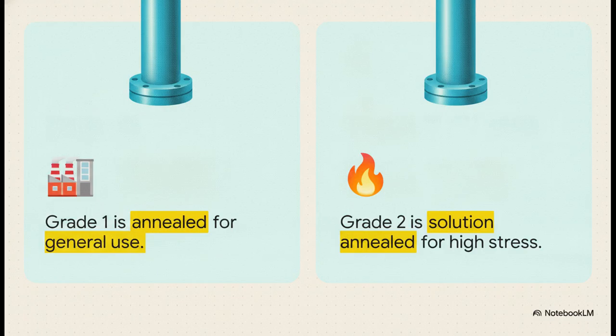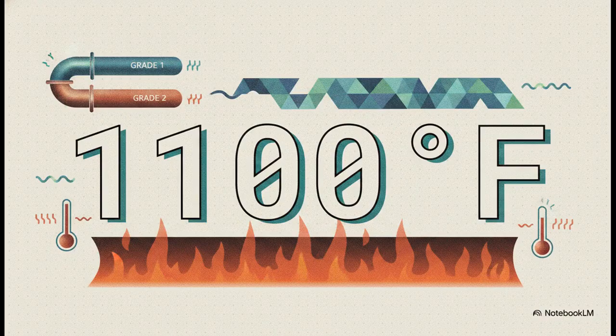It's also vital to note that, unless you specifically request otherwise, Grade 1 is the general default supplied by manufacturers. The dividing line between these two grades comes down to one critical temperature threshold, 1100 degrees Fahrenheit, or roughly 593 degrees Celsius. Grade 1 is designed and normally employed for service temperatures right up to 1100 degrees Fahrenheit. But the very second your operating environment crosses that line, Grade 2 is the material that takes over.